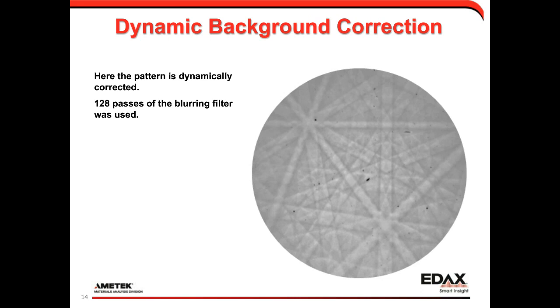However, in some cases, it can be difficult to collect a background. The most obvious example is a single crystal material. In that case, what we can do is take a pattern and then blur it with a blurring filter, multiple passes of a blurring filter, and use that blurred image as a background. We call this approach a dynamic background correction. This just shows an example of a dynamic background where in this case, 128 passes are used, and you see again, it's removed the intensity gradient and provided bands that can be detected via the Hough transform.